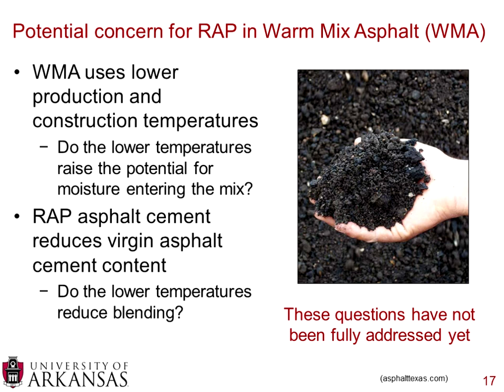To finish up this section about the use of RAP in asphalt concrete, there is a potential concern for using RAP in warm mix asphalt. And that is because warm mix asphalt is specifically designed to use lower production and construction temperatures. And two things can happen because of this. One, you have lower temperatures in your drum, you have lower temperatures during the processing of the material, and there's a potential for extra moisture to enter the mix.